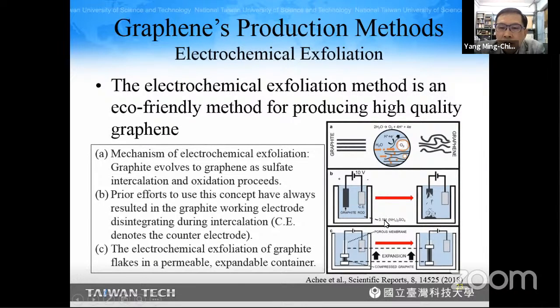And here we have a new method, a modification, using compressed graphite held together in a porous membrane as the electrode. With the progress of the electrochemical reaction, the graphite disintegrates and expands, and this will form a whole body of graphene, so that we can collect this one. This is much easier to handle and collect.